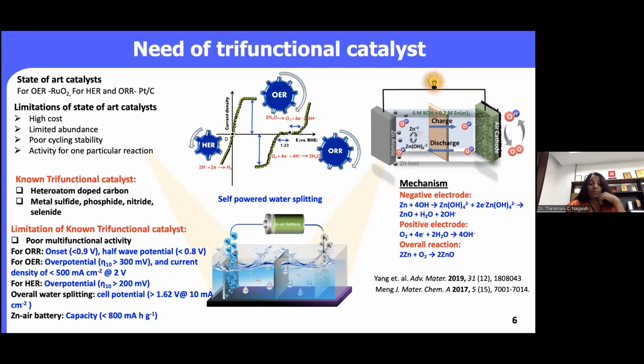The main limitation of the existing literature is poor multifunctional activity, especially with respect to the onset potential for the oxygen reduction reaction, and the overpotential at 10 milliamp per centimeter square for OER is greater than 300 millivolts. The same goes for the hydrogen evolution reaction. And for overall electrochemical water splitting, the cell potential is greater than 1.62 V at 10 milliamp per centimeter square. The same goes for the zinc air battery as well.